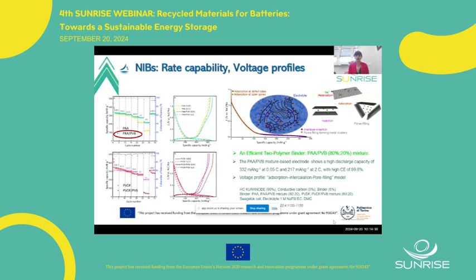In this regard, for sodium-ion batteries, we made some laminates based on hard carbon, commercial hard carbon, 90%, 5% conductive carbon, and 5% binder. So the laminates were based on just PAA, the mixture of PAA, PVB at 80-20% ratio, PVDF, and then the mixture of PVDF, PVB at 80-20%. It is well known that hard carbon cannot be commercialized due to two problems.